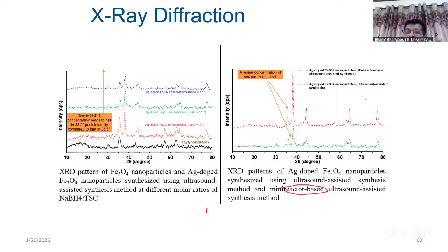So this is a comparison, right? And one more thing we have tried, that is microreactor plus ultrasound also we have done. That means microreactor was placed in ultrasound bath. So this is microreactor with ultrasound, and this is prepared with ultrasound. You can find out with the use of microreactor, the crystallinity of the material is increased here. You can observe the sharp peak here compared to the ultrasound assisted method.